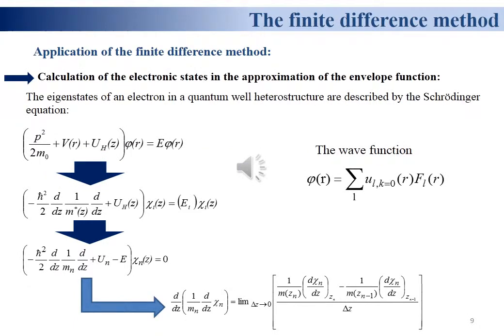The electronic states in our samples are determined by the envelope function approximation. Under the effect of the envelope function approximation, the wave functions and the energy levels are obtained by solving the Schrödinger equation, where V(r) is the crystalline potential and U(z) is the potential of the heterostructure, where z determines the barrier and the well interface position. The position taken as the origin of the potential is z1. The potential of a heterostructure often results from the band discontinuity, the delta of energy offset at the interface of the two materials, due to the difference in the position of the conduction bands. However, this time the presence of internal electric fields in each of the two materials will influence it.